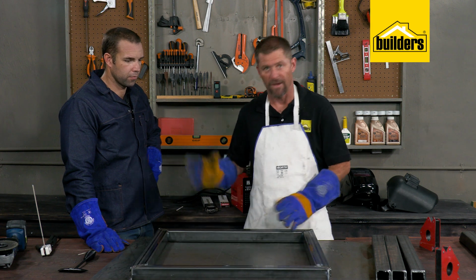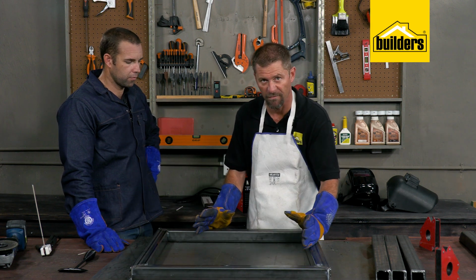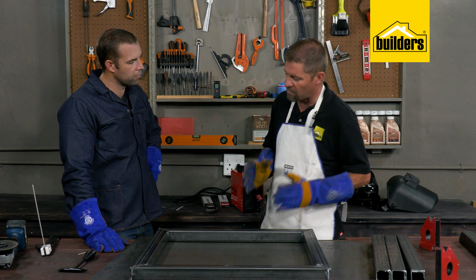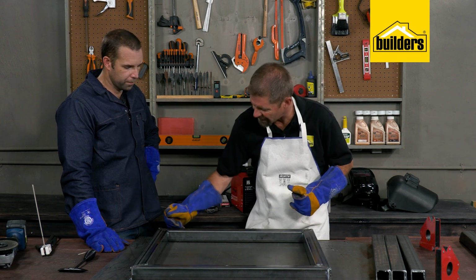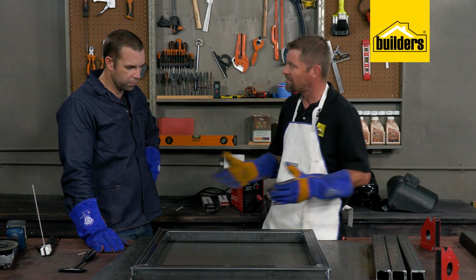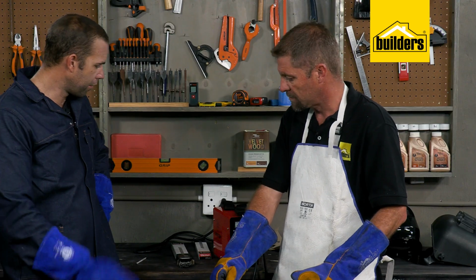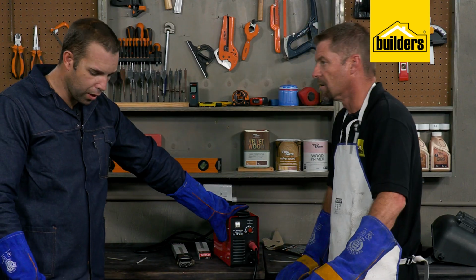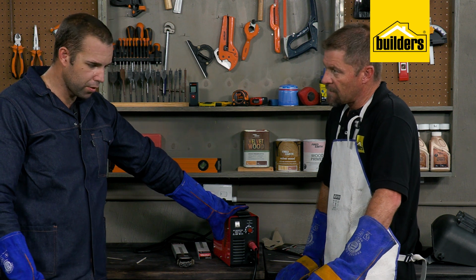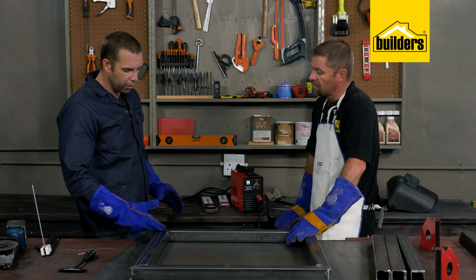So the first square of our framework is done, and Brad is going to do exactly the same and build a second square. But Brad, first, when I weld, often I find that my welding will stick and I've got to twist it and yank it. Why is that happening? Kev, that'll usually occur if your amperage on your welding machine is set too low. In order to fix that, you can turn your amperage up and try and move along the seam a little bit faster. Let's get that second square done.